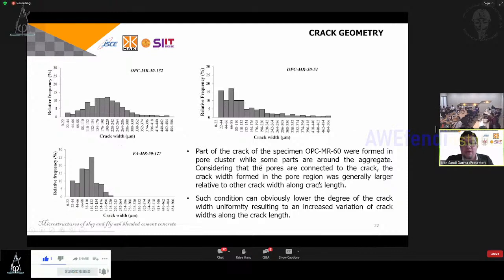So as you can see here, part of the crack in the OPC specimen was formed in the pore cluster, while some parts are around the aggregate. Considering that the pores are connected, the crack width formed in the pore region was generally larger relative to the crack width along the crack length. Such a condition can obviously lower the degree of crack width uniformity, resulting in an increase in variation of crack width along the crack length.